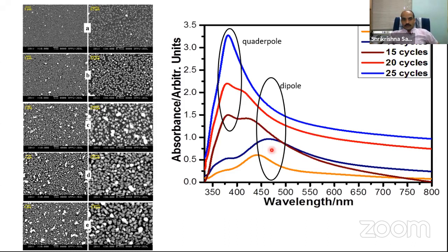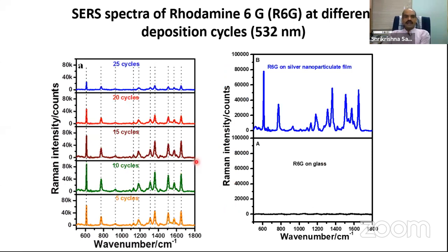Now with this absorption spectrum, I can understand the SERS. What you can see is that I'm using this 532 nanometer laser to record this Raman spectrum. For 5 cycles, the intensity is 60,000. For 10 cycles, it is more than 80,000, like 90,000 or whatever it is. Then again, it is decreasing.